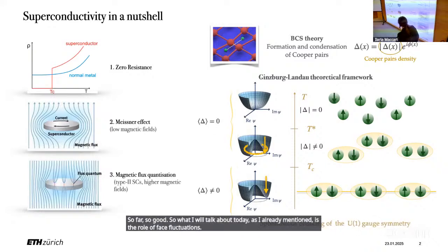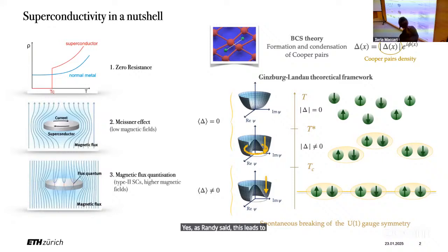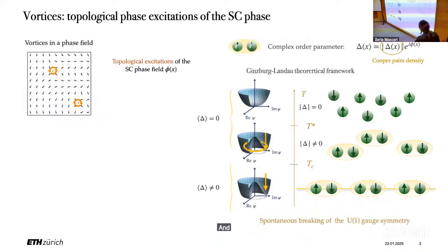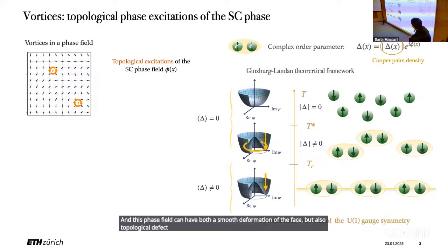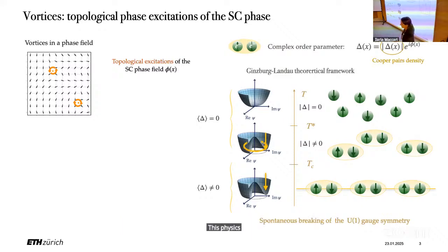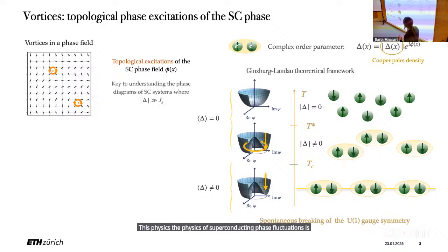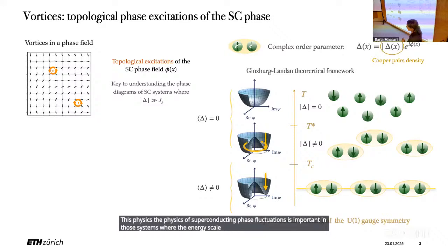So what I will talk about today, as I already mentioned, is the role of phase fluctuations. As I already said, this leads to a spontaneous breaking of the U(1) gauge symmetry. And this phase field can have both smooth deformations of the phase, but also topological defects. These topological objects are, in this case, vortices, and are objects that cannot be smoothly deformed in an ordered state. The physics of superconducting phase fluctuations is important in those systems where the energy scale associated with the quasi-particle excitation, so associated with the amplitude, if you want, of this order parameter, is larger than the energy associated with the phase fluctuation, so with the phase rigidity, which is the superfluid stiffness.